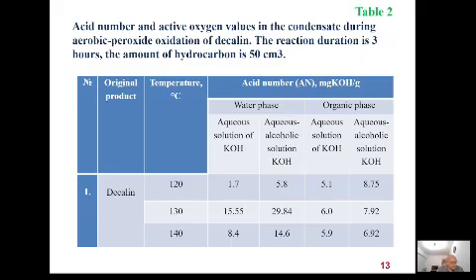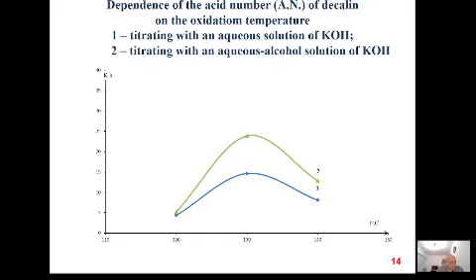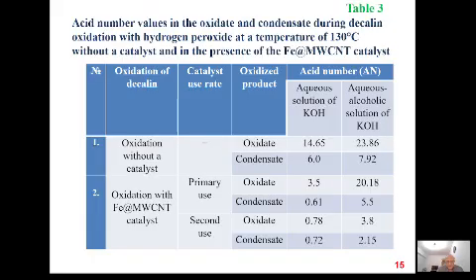Slide number 14 shows graphical pictures of the acid number deviation depending on the reaction temperature. The acid number values in the oxidate and condensate during decalin oxidation with hydrogen peroxide at 130 degrees Celsius without a catalyst and in the presence of the ferrum-containing multi-wall carbon nanotube catalyst show results consistent with the hydrocarbon aerobic oxidation products sequence, which is well known from the existing theory.